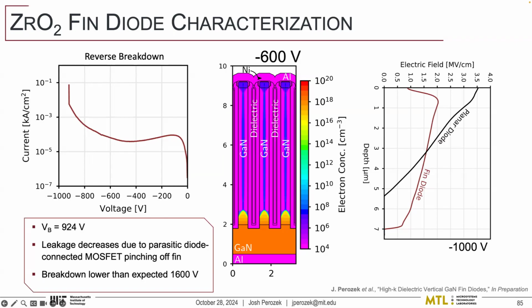So the dielectric on the sidewall there is essentially your gate metal or your gate oxide for a FinFET. And as you deplete the channel more and more, you're essentially lengthening the channel of your gate and you're removing short channel effects. So when there's not very much depleted, you can't deplete these fins laterally and you can leak through it very quickly. But as you deplete your entire drift region length there, now your carriers have to go through 6 microns of a gated transistor, which reduces the leakage. And once you hit 600 volts, as you see in the simulation, you've depleted the entire drift region there. And that's when your leakage starts to increase again.